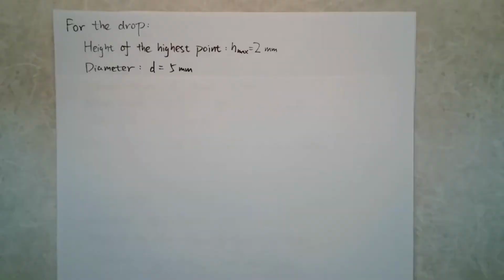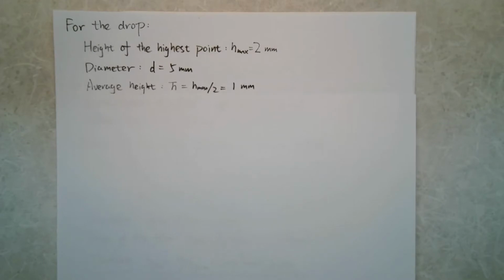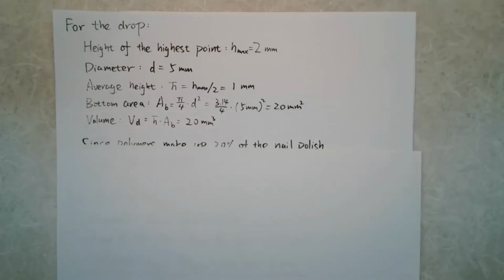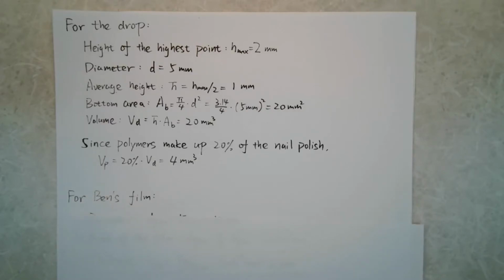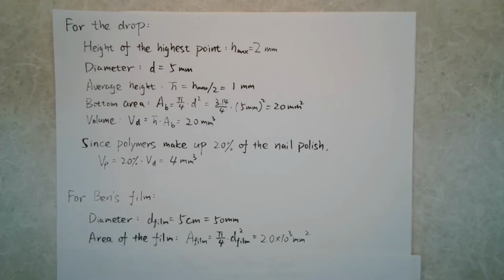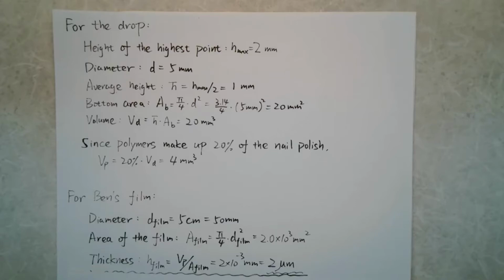Now, let's do the calculation. First, we approximate the average height of the drop to be 1 mm. Then we calculate its bottom area and then volume. Considering polymers make up 20% of the nail polish, the volume of the polymer film would be 4 mm³. Then, using the area of Ben's film, we get its thickness, 2 micrometers. That's pretty thin, 30 times thinner than the human hair.